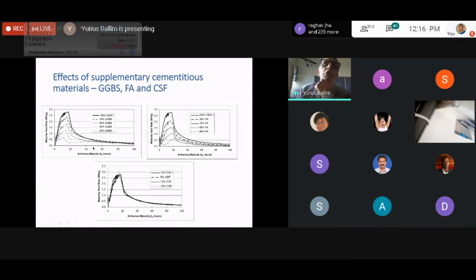So if you're going to think about reducing peak temperatures in large concrete elements, fly ash and slag, I imagine rice husk ash would have a similar effect. Would be something really interesting to look at as well, and other pozzolanic materials would have this kind of effect. And you want to maximize the amount of these supplementary cementitious materials.